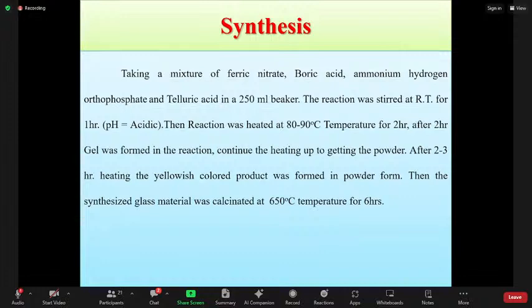For the synthesis, take a mixture of ferric nitrate, boric acid, ammonium hydrogen orthophosphate, and telluric acid in a 250 ml beaker. Then the reaction was stirred at room temperature for 1 hour while maintaining an acidic pH. Then the reaction was heated at 80 to 90 degrees for 2 hours. After 2 hours, a gel was formed in the reaction. Then continue the heating until getting the powder.